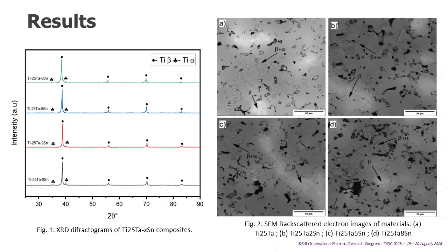This indicates that this element diffused completely into the titanium matrix during the sintering process, or if any intermetallic compounds were formed with titanium, they were not detected due to their low concentrations in the final composition of the materials. The SEM analysis shows the microstructure of each processed material, which are related to the components that make up the alloys.